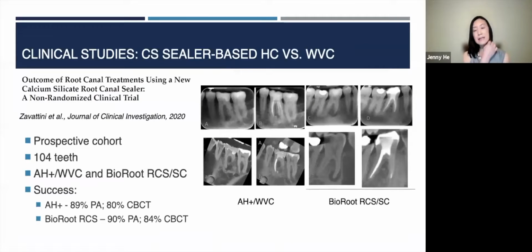And this is another outcome study on another calcium silicate-based sealer. It's BioRoot RCS, a product from Septodont. It's not a pre-mixed sealer; you do need to mix it before use. This study compared cases obturated with BioRoot RCS in a single cone technique and cases obturated with AH Plus in a warm vertical technique. They found no difference regarding success rate between the two groups, and their reported success rate of 90% is very similar to what we reported for BC.